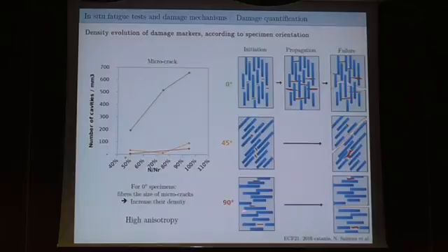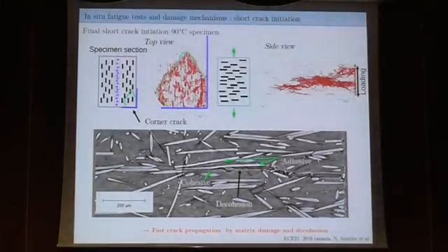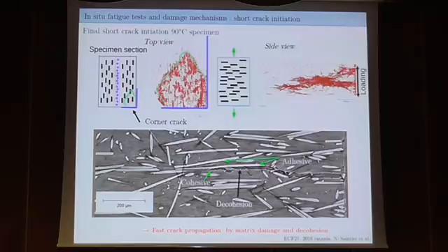So you will fail quickly or transform quickly from a local damage to a complete failure of the specimen at 90 and 45°, while at 0° you need much more energy. I will show you just after this one by looking at the final crack. This is a crack just before failure. The crack that we have been detecting was outside the monitored zone, because there is a small chance, if you are matching on 1 mm, that you will catch up with the crack. But by monitoring the macro scale parameters, load and displacement, you can see that something is happening somewhere in the specimen. You can try to track this area and find the crack.